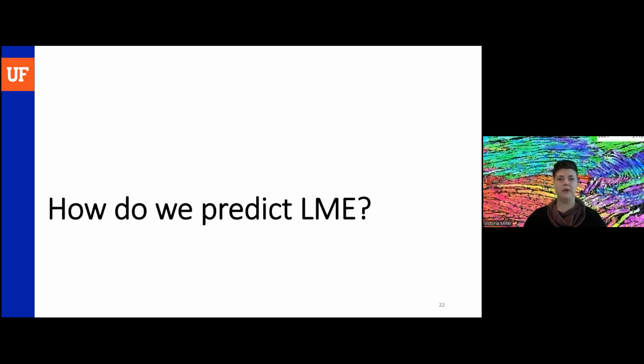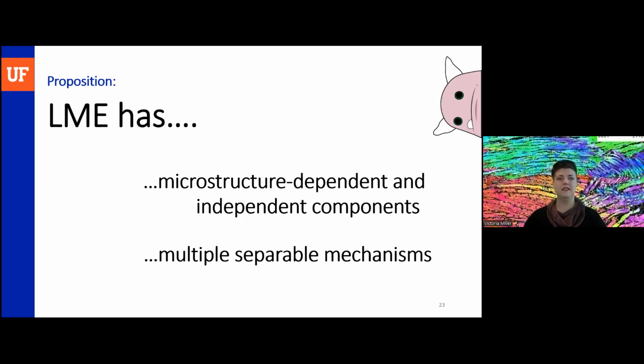So we proposed a bit of a framework to interpret this. We propose that liquid metal embrittlement has microstructure dependent and microstructure independent components. And we propose that liquid metal embrittlement has multiple separable mechanisms. And the rest of this talk is going to be demonstrating those two points for you.